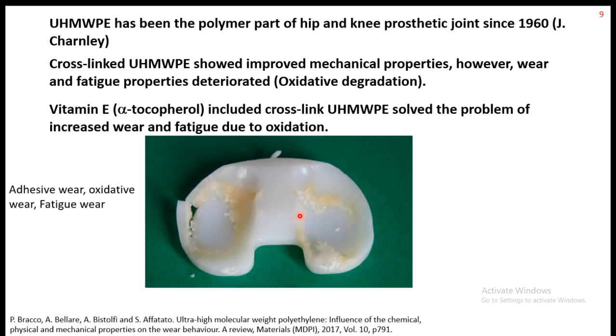Here you can see one of the knee implants, and the wear takes place by what is known as adhesive wear. That means the metal actually sticks to the polymer part, and gradually it removes the polymer part because of the fatigue action. Oxidative wear and fatigue wear also take place in this part. Oxidative wear, because you can see some discoloration and some changes in the molecule size. This UHMWPE is a very large molecule, but because of the mechanical shear and some chemical oxidation, the molecules will basically break down. So these are all part of the failure mechanism that takes place in UHMWPE.